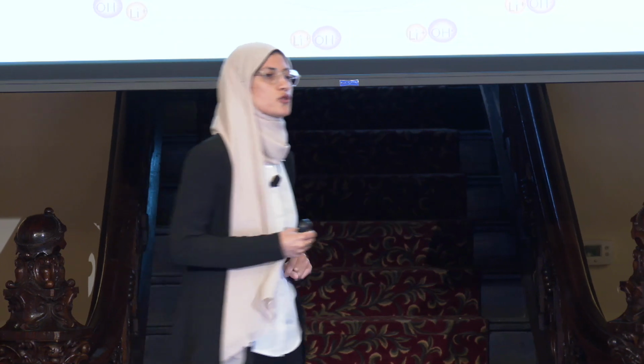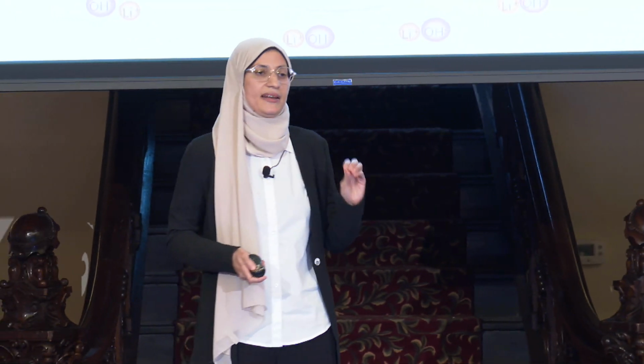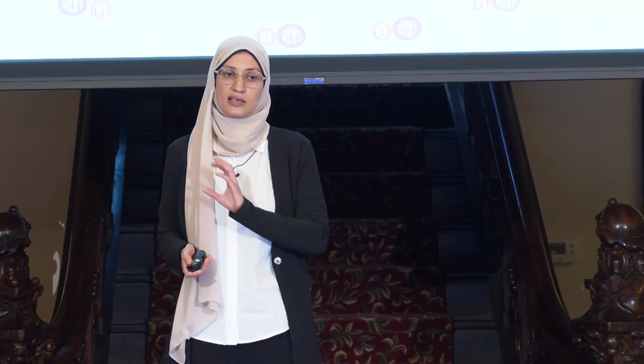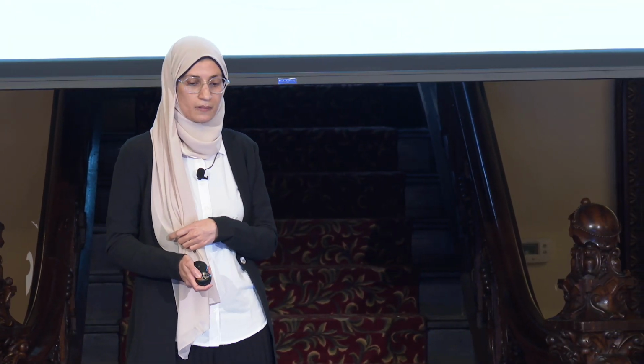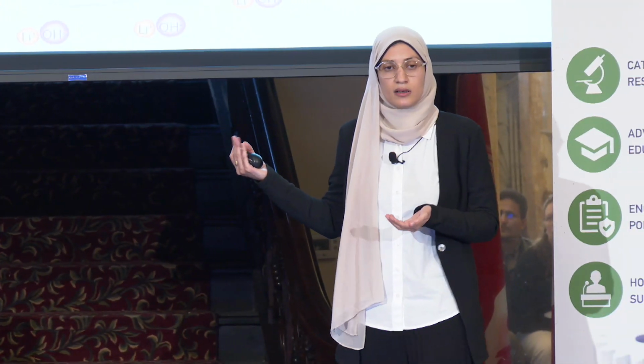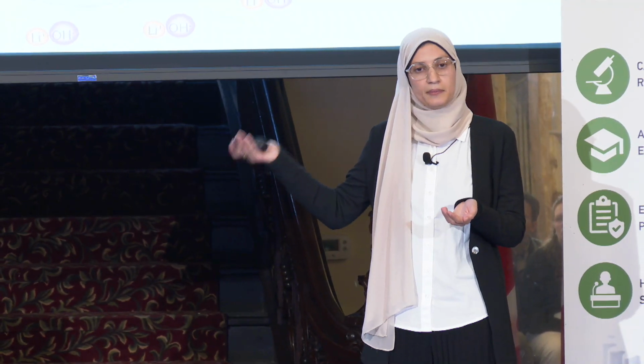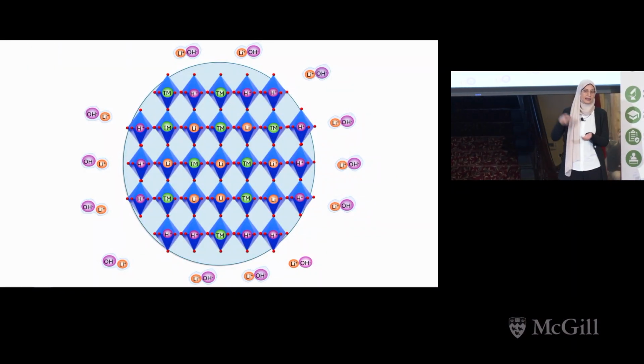And this helped us solve the problem. We thought, what if we could just reverse this process? Indeed, instead of applying a second step and washing the material in pure water, what we did is wash the material again, but this time in a highly concentrated lithium hydroxide solution. So we wash the material with a highly concentrated lithium solution in order to let lithium leave the solution and jump back into the structure.